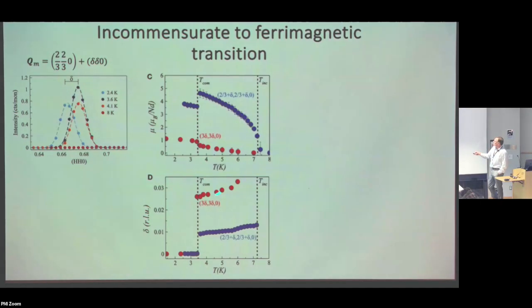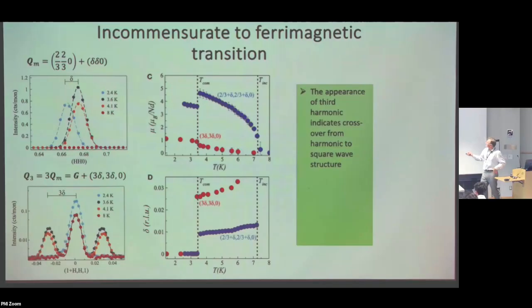There are also some higher order harmonics that are seen. And that means that it's not just a sinusoidal spin density, but there's some kind of edges to it. And those tend to get stronger as you cool down, and it gets more saturated, more square wave-like. And then eventually you get into this commensurate state.